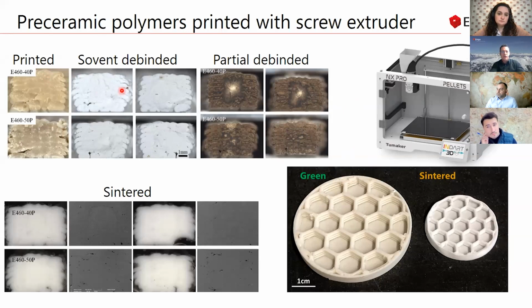And you can see here different results which we achieved. So you see here different binder compositions, and for example, in the solvent debinding process, you can see that we can remove a part of the binder already, but after the partial debinding, with one binder system we still have some parts inside the samples which we printed which are not fully debinded. And when you sinter them, you then see some cracks inside, which means you lose the mechanical properties. So also here the point is that the screw extruder, from my point of view, is a very good alternative to a filament printer, but the binder system still has to be further investigated so that you get nice parts out of it without any kind of